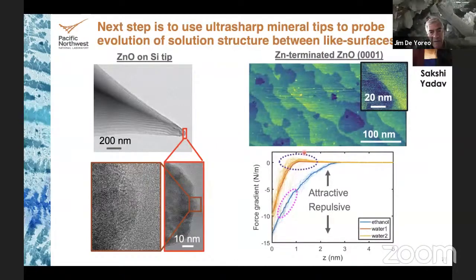And this is preliminary, initial data showing that we can measure the force gradient versus distance, and we can see the differences between different solvents. We get an attractive interaction in water. We get a repulsive interaction in ethanol. They have different dielectric constants, so we expect very different dipole interactions. So we're pretty excited about being able to do this now.